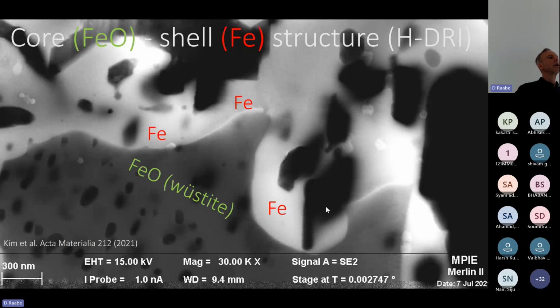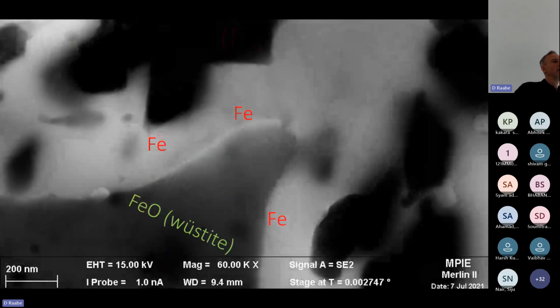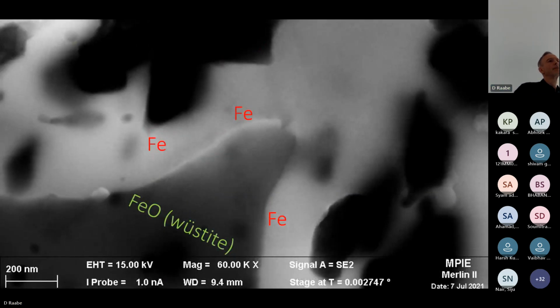And that is just the same thing at a higher resolution in the microscope. And you also see, of course, all that porosity that is evolving here, which is, of course, due to the mass loss. So every oxygen atom that is left produces an anion vacancy. The vacancies are collapsing. We assume mainly at these proceeding interfaces between the metal and the wüstite oxides, and they coalesce and form then a complex porosity pattern. But we will get back to these porosity patterns as you see here. So that's about where we stand with understanding these core-shell structures.